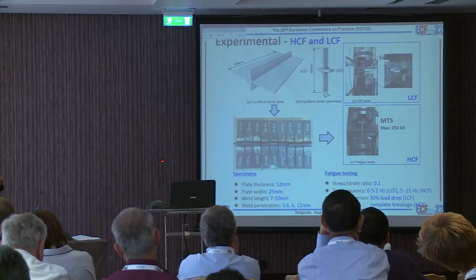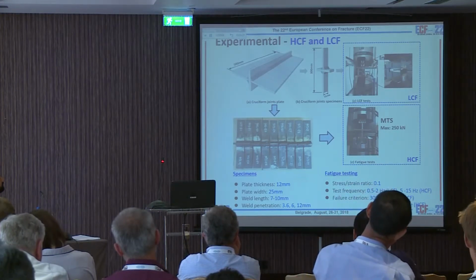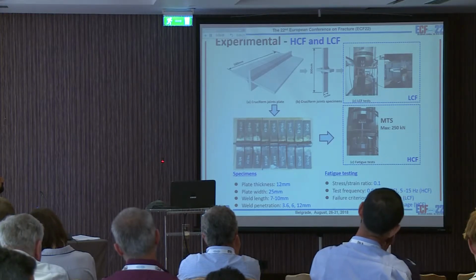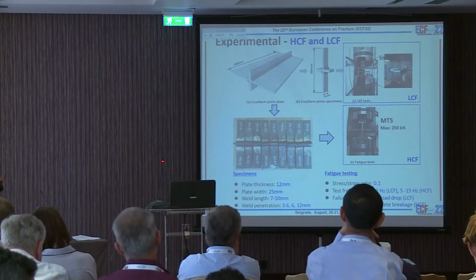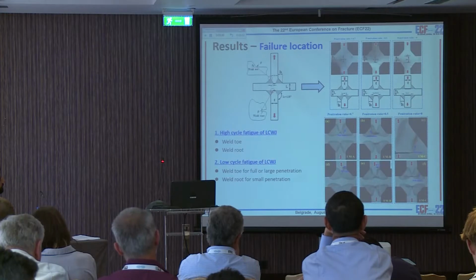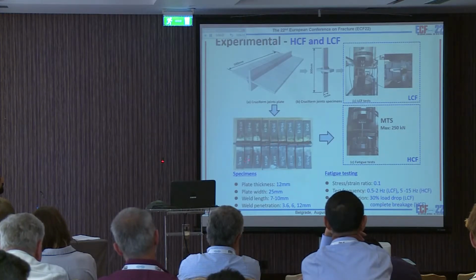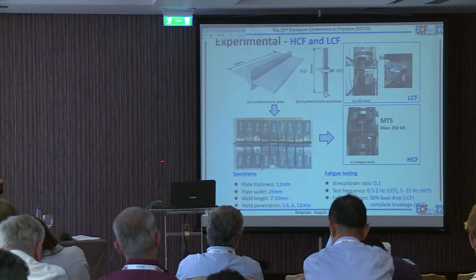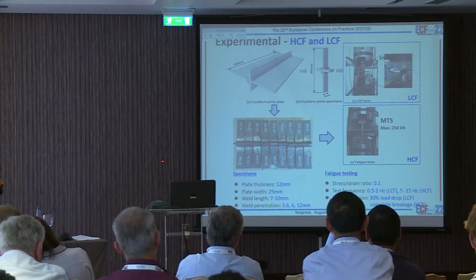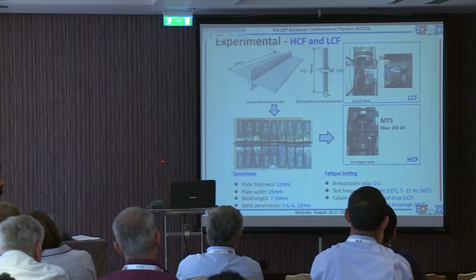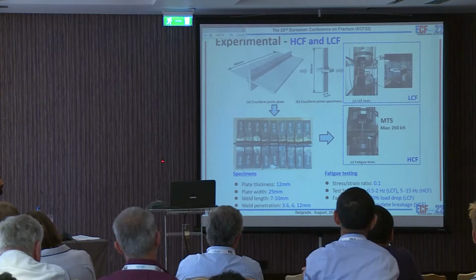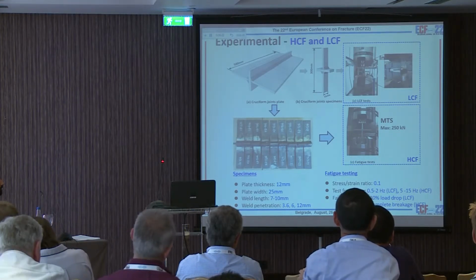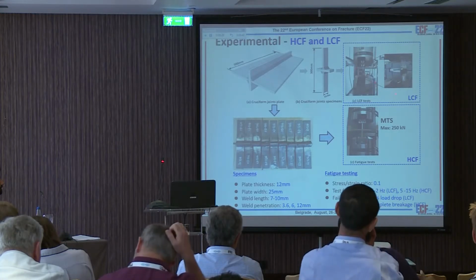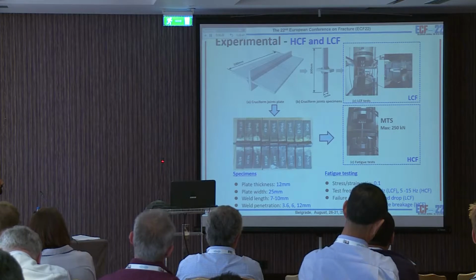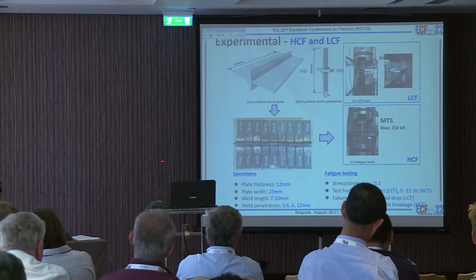Next, I welded some cruciform welded joints and used wire electrical discharge cutting to cut the specimens. Then we used these specimens for the low cycle fatigue test and the high cycle fatigue test. It should be noted that for the high cycle fatigue test I just used force controlled conditions, and for the low cycle fatigue we used the extensometer to control the displacement, so they belong to different load conditions.